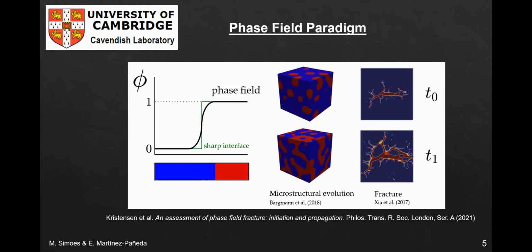The method was first developed in the microstructural evolution community, where the change in shape and size of microstructural features, such as grains, can be predicted by defining the evolution of the phase field in terms of other fields, such as temperature, through a thermodynamic free energy. While in fracture mechanics, in the application that I will be mainly discussing, the phase field tracks the crack-solid interface, enabling the capture of complex cracking morphologies. You can see in the figure examples of crack merging, nucleation from arbitrary sites, branching. So it is a very powerful tool from a computational perspective.